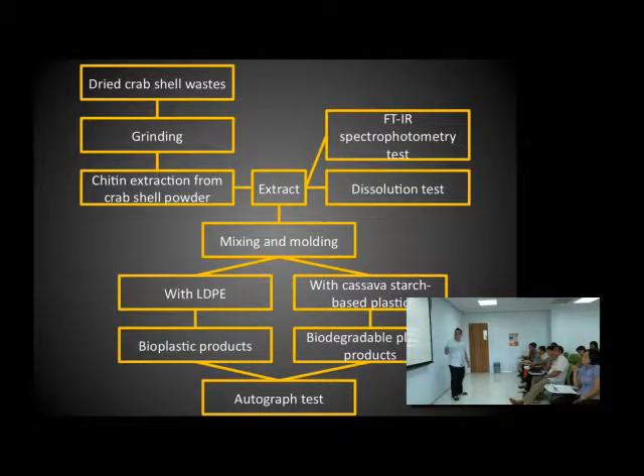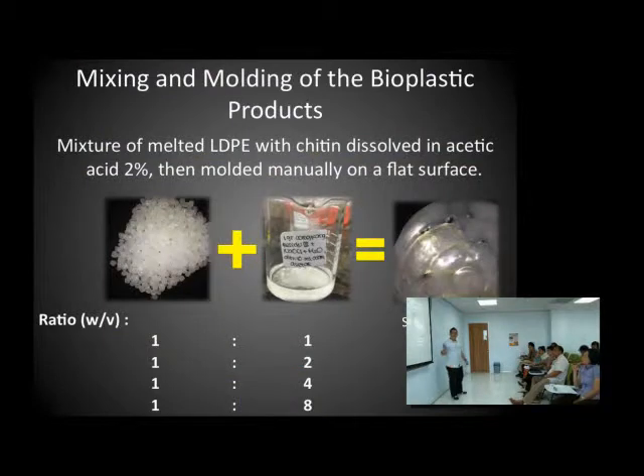The next step is the mixing and molding. Here we will have two final products resulting, the bioplastic and the biodegradable plastic. Bioplastic is the mixture of melted LDPE with chitin solution in acetic acid 2% that is molded manually on a flat surface. And I tried to mix it with 4 different ratios. Here's the sample picture of the bioplastic product.